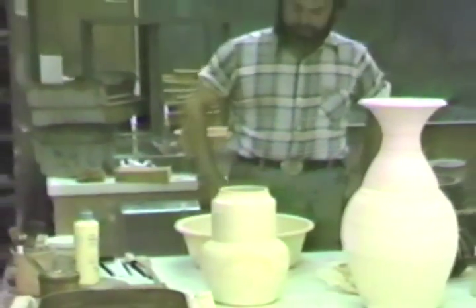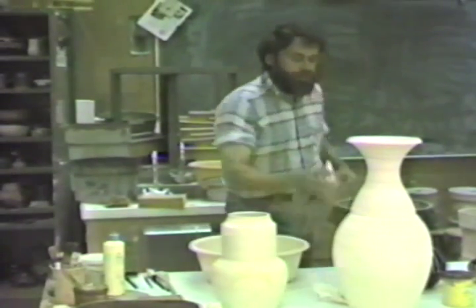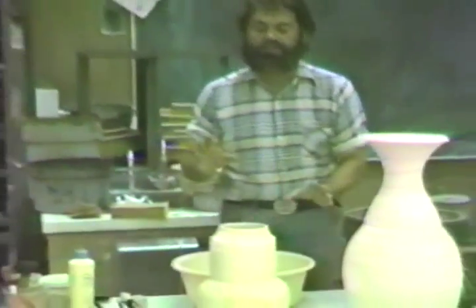And I'll have to do it again after I put the glaze on the outside, because you could end up with little droplets there, and you think you've taken care of your problem by putting the wax resist on, but if the droplets are on top of the wax resist, you put your lid on, then it's fired, those little droplets will seal it to the pot. So again, you gotta be very careful.